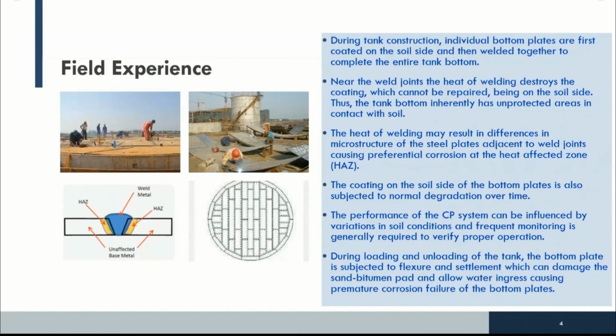When we look at a lot of the other traditional barrier systems, like traditional coatings, these can't handle the construction process, whether that's the physical damage during installation or the heat input during the welding process. Both of these create significant coating holidays, and you get lots of bare spots, and then we get localized corrosion on the underside of our tanks, which we can all agree is not good. So there's a pretty big need and driver for an easier to install, easier to maintain, and manage corrosion mitigation tool for the underside of our storage tanks.